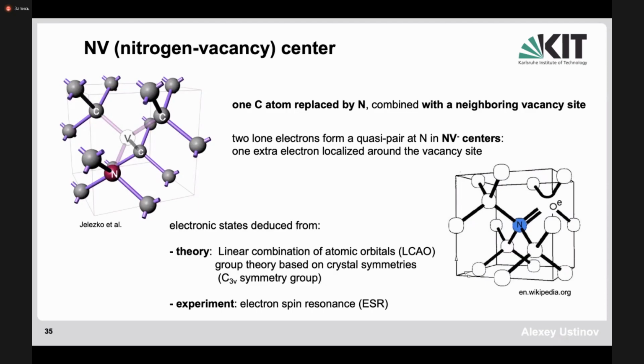And then if you do it right at the appropriate temperature, the most typical defect that will stay will actually be nitrogen, which comes in because you could do it in a nitrogen atmosphere, and a vacancy, which will form a kind of bound state with this nitrogen. The material has the lowest energy state when the two electrons get trapped and form a quasi-pair around this defect location. So there will be basically one electron localized at the nitrogen atom and one electron localized near the vacancy site.